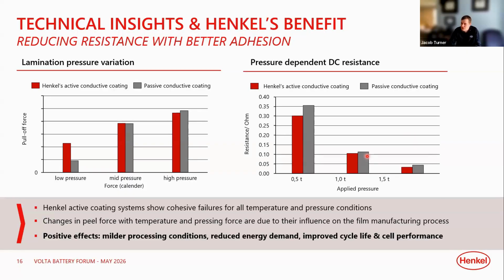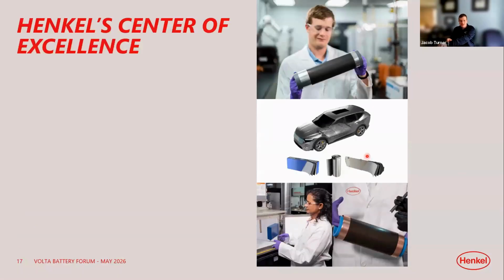This was what I alluded to in terms of the conductivity. As you form a better interface, adhere, and enhance the adhesion to the active material, you also see a reduction in this resistance value. So these red bars are a bit lower than the gray ones. As you're increasing pressure, it maintains that same percentage improvement. Any questions there as we take the last few minutes? I'll switch gears into some of our capabilities and my personal perspective on future outlooks.